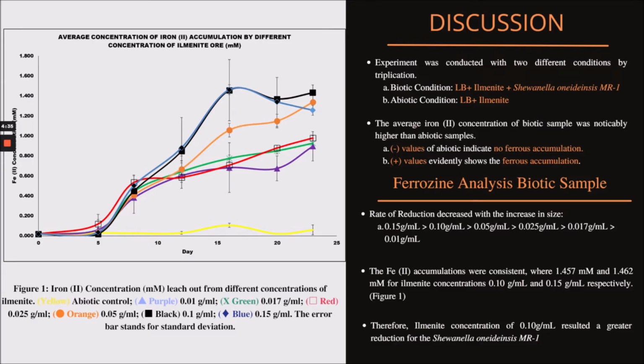Let's look at figure 1, where the ilmenite grains of 7 different concentrations have been incubated with Shewanella oneidensis MR1. Based on a previous study, 0.10 gram per ml of ilmenite concentration showed a maximum iron leaching at 1.4 millimolar. We set up a similar experiment along smaller concentrations ranging from 0.10 gram to 0.15 gram per ml. As expected, the leaching was highest in 0.10 gram per ml, which is the black line, and 0.15 gram per ml, which is the blue line, accumulating about 1.457 millimolar and 1.462 millimolar respectively.